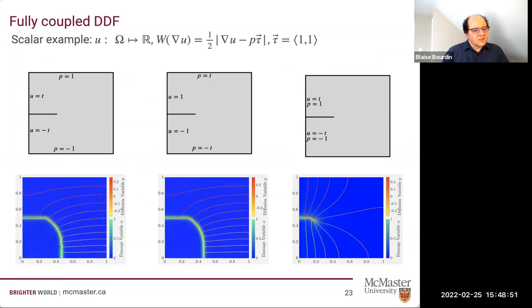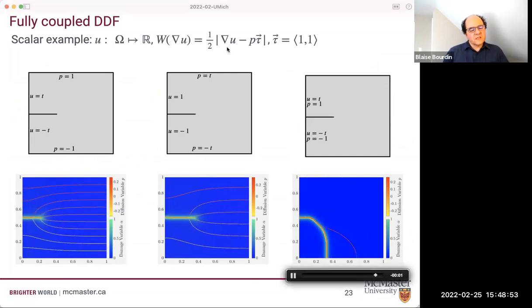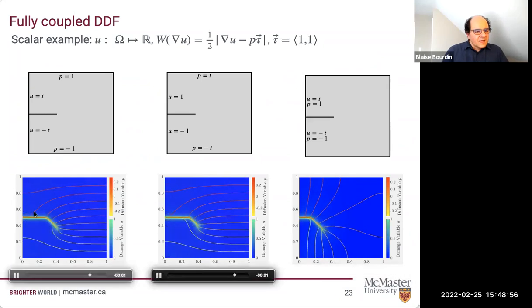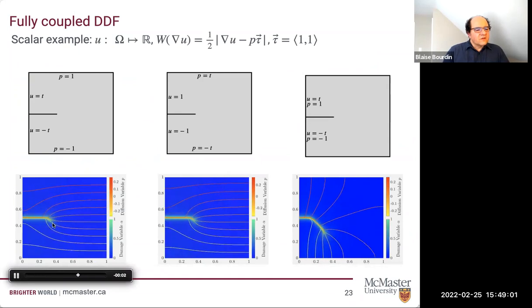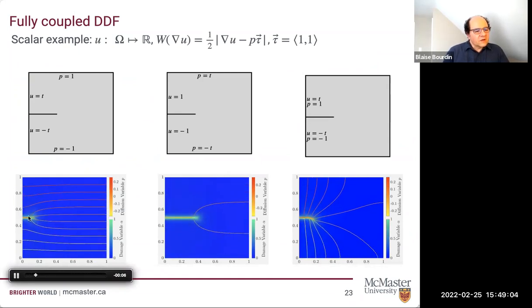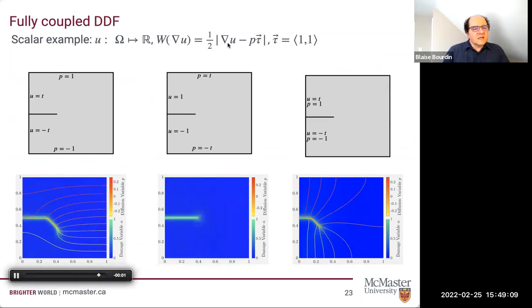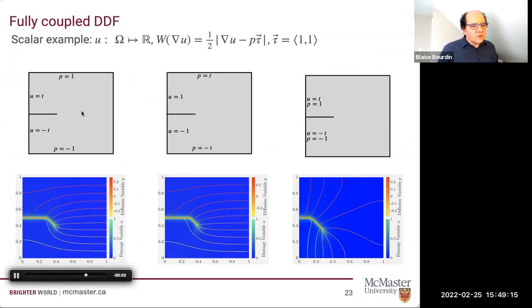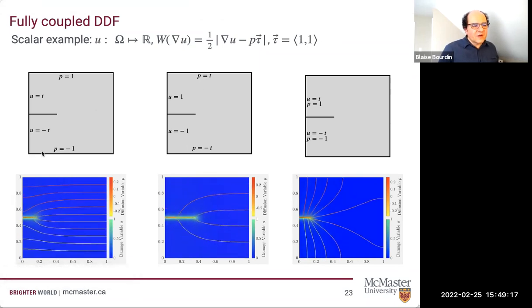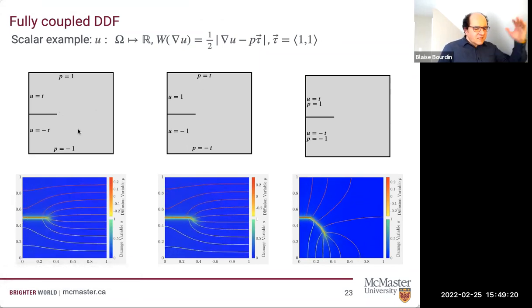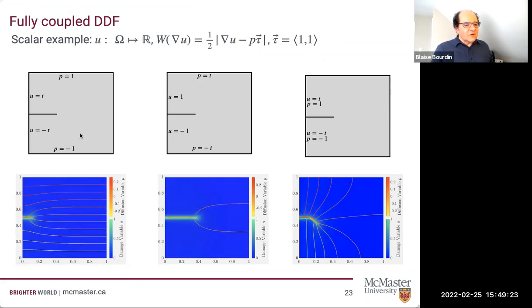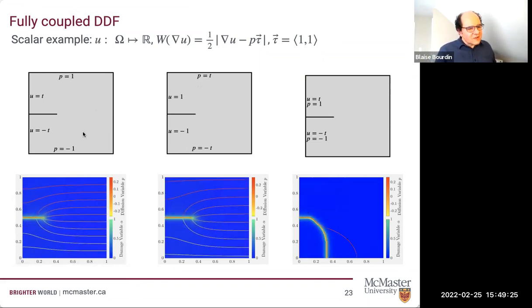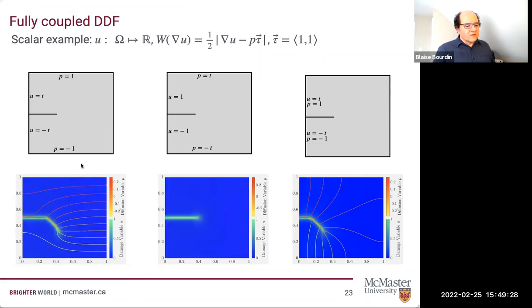And I just want to show examples. This is a simpler version, a scalar version of the problem. The level lines are the level lines of the diffusion field, of the P field, and the color is just the fracture. The way this is designed, you have competition between two problems. The mechanics problem wants the crack to grow horizontally. The thermal problem wants your crack to grow diagonally. And then there's this free discontinuity principle that says when a crack gets close to an interface, it wants to shoot toward the boundary of the interface.